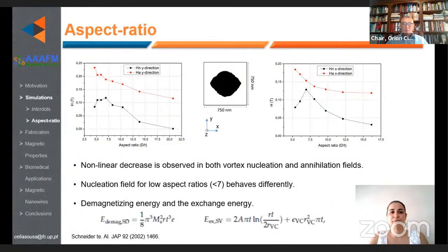The thickness and the diameter of the disk are key parameters to define the dimensions to achieve the vortex state. Thus, the vortex characteristic fields, annihilation and nucleation fields, are plotted with respect to the aspect ratio of the nanodisks, the diameter divided by the thickness, in both X and Y directions. As the aspect ratio increases, a nonlinear decrease is observed in both nucleation and annihilation fields, in agreement with what has already been reported for vortex behavior.